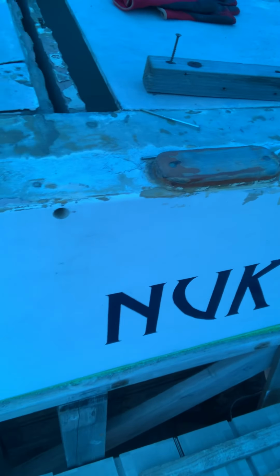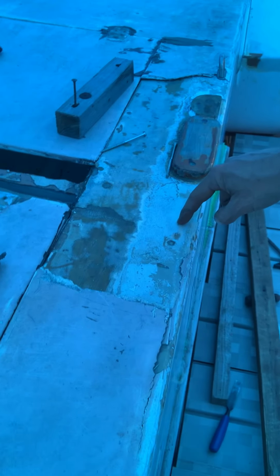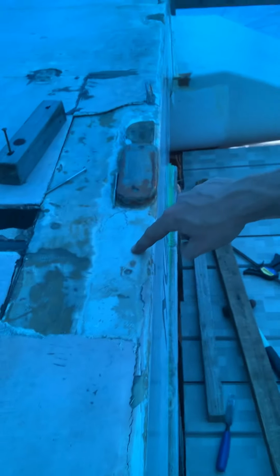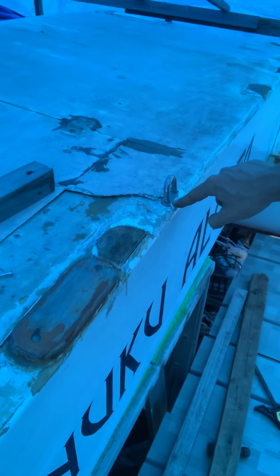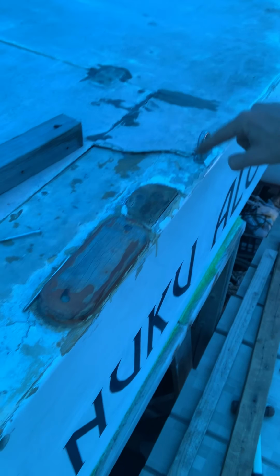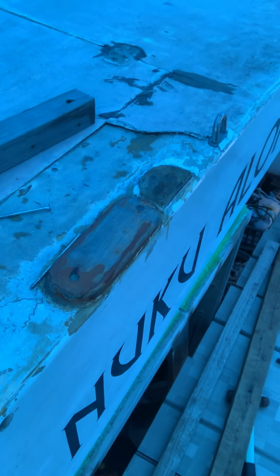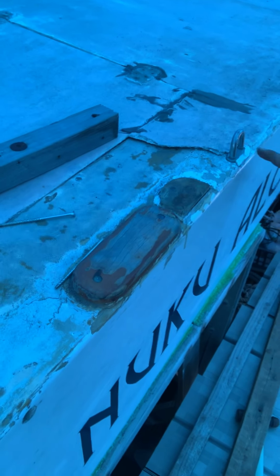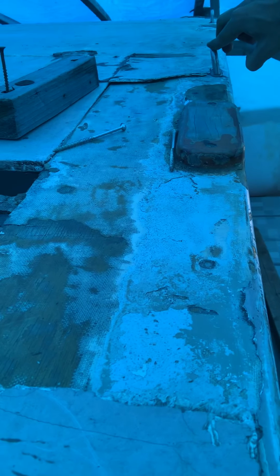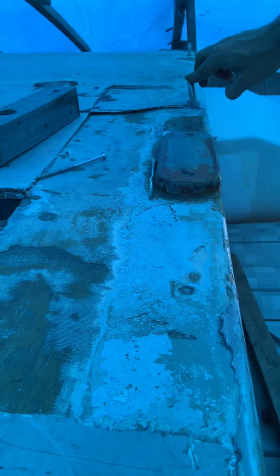But more importantly, what I want to point out here is the builder has installed hardware directly over this main strength bulkhead, and it's the type of hardware that is permanently bonded in. These U-bolts are fixed. They cannot be removed, and the epoxy annuli that are in the holes that they're bedded into cannot be inspected for cracks or watertight integrity. This is dangerous, folks, because you can have, as you can see here, a delta load that will bend this metal attachment point, causing it to deflect and possibly cracking that epoxy annuli in there if the material is somewhat brittle. If the builder used, say, West System 105, a very, very hard, stiff epoxy without any fillers, that annuli could have cracked and there could be water incursion going down to the beam.